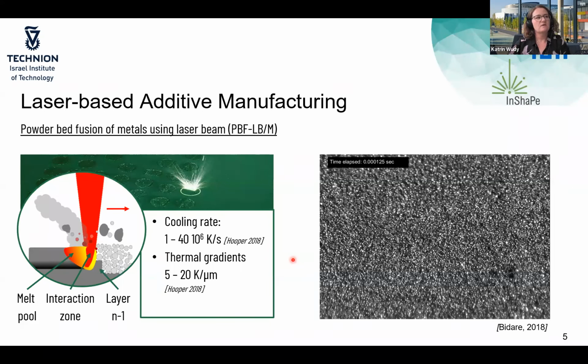So why is this such a highly dynamic process? That's the question we would like to tackle: how to smoothen up this process a little bit, maybe by tailoring the energy input in space, so by a special tailoring of the energy input. But first of all, the challenges. Typically we use a Gaussian beam profile for energy input, which means the intensity distribution is like a Gaussian profile. And this leads to component defects or process inhomogeneities like overheating of the melt, which was shown here, spatter and balling effects. I will describe later on what balling defects are.